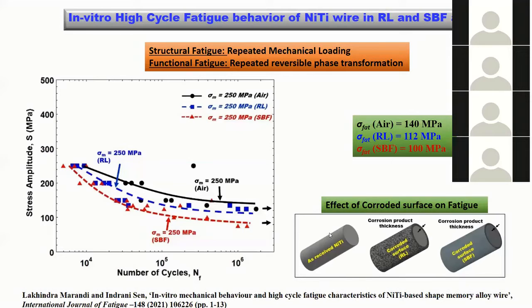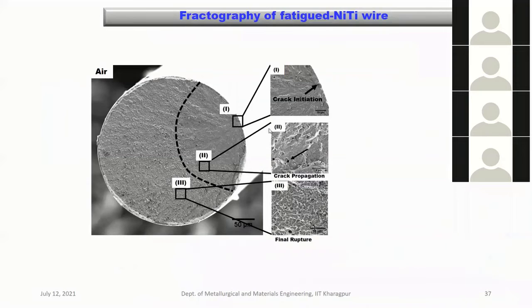So once again, we explain this with the help of the corrosion layer that is forming. This corrosion layer also has a very significant role to play in the case of mechanical loading, in the case of fluctuating loads, where it is supposed to break up and can initiate the crack. This crack initiation has also been tested through detailed fractography. And we can see the striations, the crack initiation site, etc.